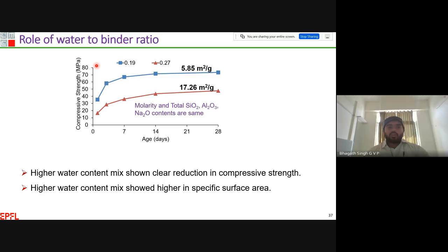And coming to the role of water to binder ratio, here I have used two different water to binder ratios. Typically we use a water to cement ratio, but instead of cement I have used the binder here. The binder is nothing but the binding material, which is fly ash as well as alkali activators. And if you increase the water to binder ratio from 0.19 to 0.27, you can clearly see a reduction in the compressive strength at any particular time.